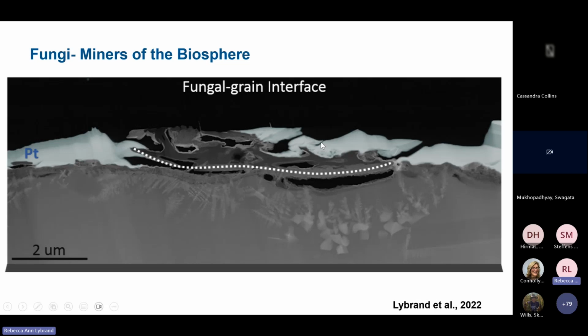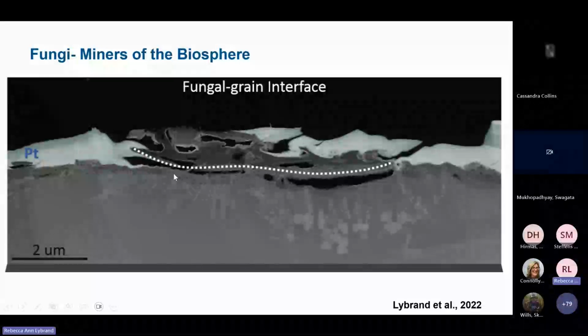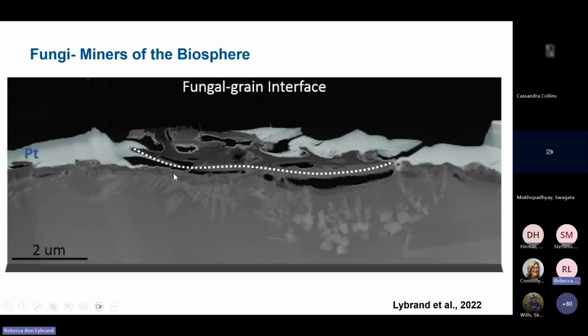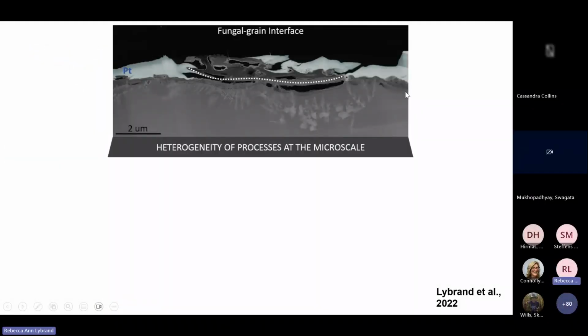And then we were also able to, again, use TEM, or transmission electron microscopy, to identify what these inclusions are. We actually saw fungal contacts at several areas that had these inclusions. And these are magnetite grains, in different forms. You can see the different morphological structures here compared to the inclusions over here. So this particular study really demonstrated the heterogeneity of processes occurring at the microscale.